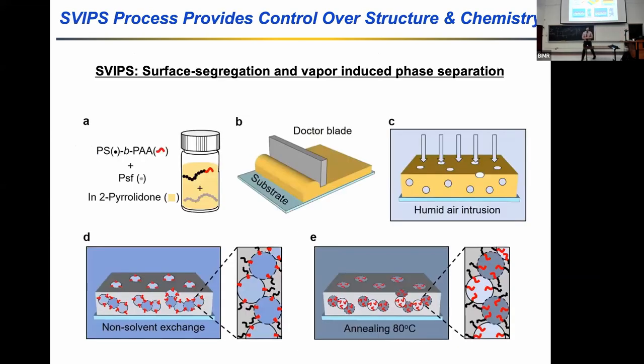And we're not going to do it with self-assembled block polymer materials. We're going to use a slightly different technique. And so we're still going to use non-solvent induced phase separation. And we're going to dissolve a homopolymer, polysulfone, with a diblock polymer, polystyrene-polyacrylic acid. And we're still going to pull it down into a thin film using a doctor blade.